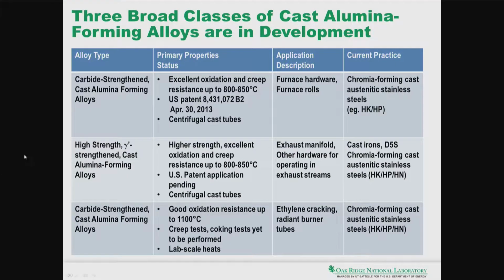So we have three broad classes of alloys that we are working on, and these are targeted at specific property requirements that we are aware of in those classes of components that we are targeting them for. And so here, I've just briefly summarized this in this table. We have carbide-strengthened cast alumina-forming alloys that primarily top off at about 800 to 850 C in terms of temperature of applications. These are covered by issued US patents, shown here. And the form we think that these will be used in is centrifugal cast tubes. Of course, these are furnace hardware, furnace rolls, and traditionally they are dominated by the chromia-forming cast austenitic stainless steels.